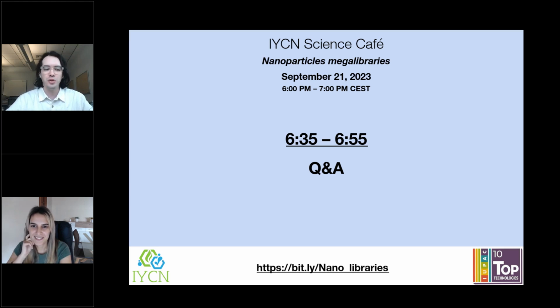And then once you do that, the patterning can take anywhere from 30 minutes to 2 hours, depending on what you're doing. Most of the time it's around 30 minutes of patterning. And then the long step, for most of these, for the nanoparticles in particular, is the thermal annealing. So we usually put it in a furnace overnight so we can do high temperature treatment, make nanoparticles. And then the next step is the screening method.